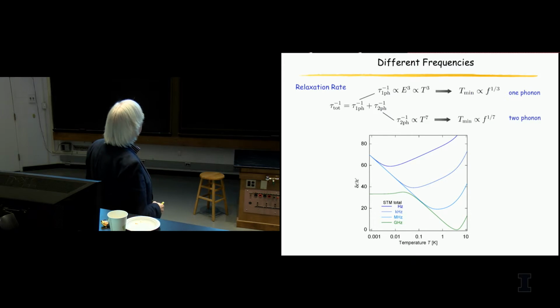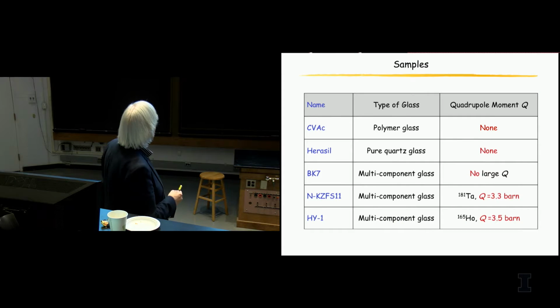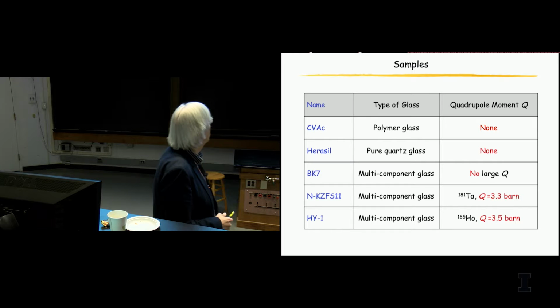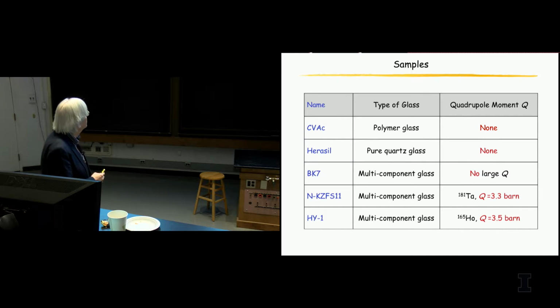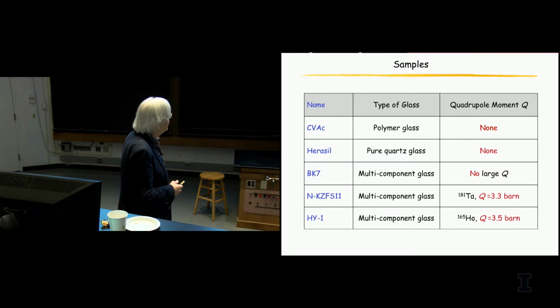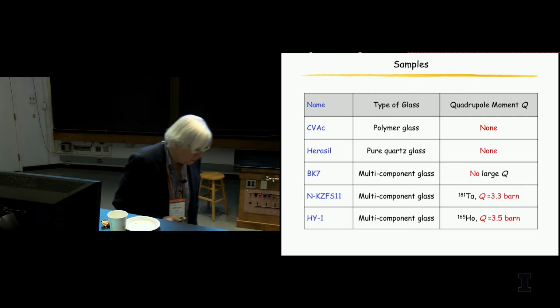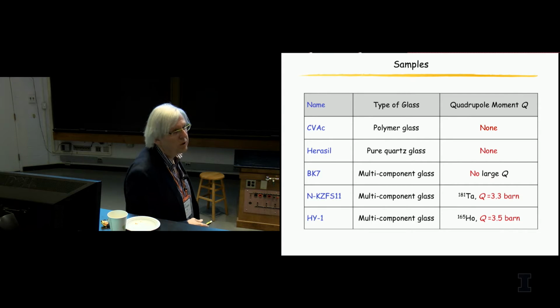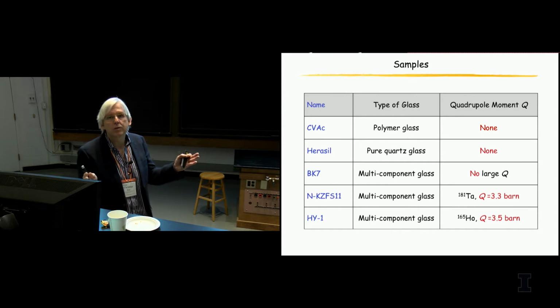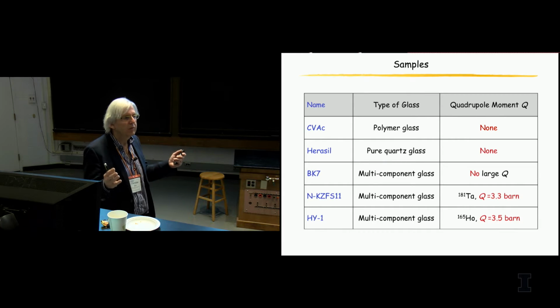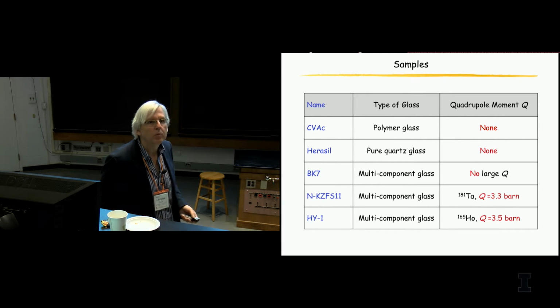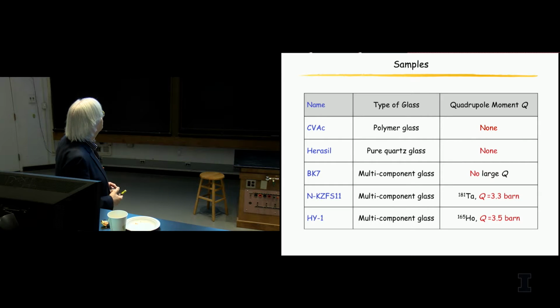Now, we did then investigate a number of glasses. These were glasses, the first three here. They have no quadrupole moment or only very small ones. And then we looked for systems which had a certain amount of holmium in them, which has a large quadrupole moment. In this particular case, you have 1% of holmium in the glass. The rest is almost the same. You can consider it as BK7 or something like that, but with 1% of holmium. Now, the question was, what would we see?